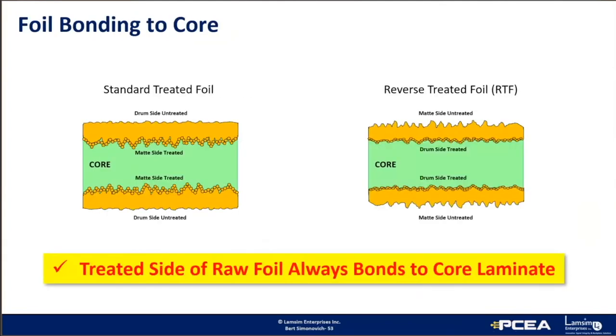The nodule treated side is the side that is always bonded to the core. For standard treated foil, it's the mat side. And for reverse treated foil, it's the drum side. It's important to keep that in mind when you're doing your modeling for your roughness.